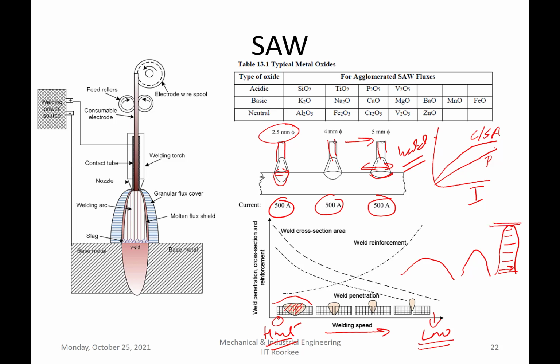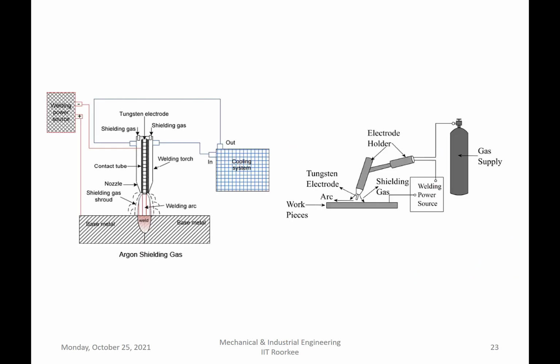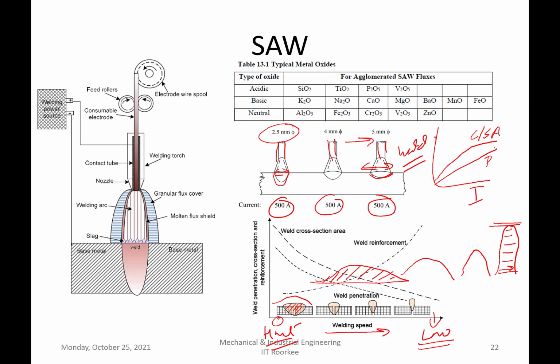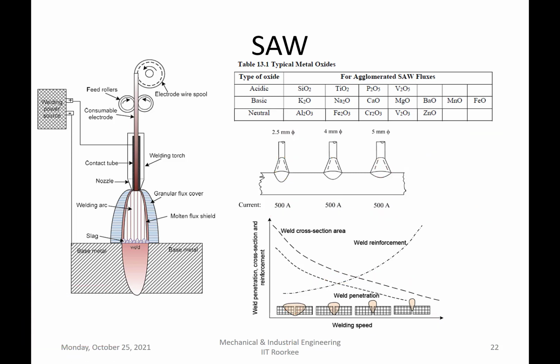Okay, when heat input is very high, it is flatter like this. So your bead is flatter with the low bead angle. On the other hand, when heat input is low, bead angle will keep on increasing. So increasing bead angle actually is not good, because it increases the stress concentration. So this is what you can see here.